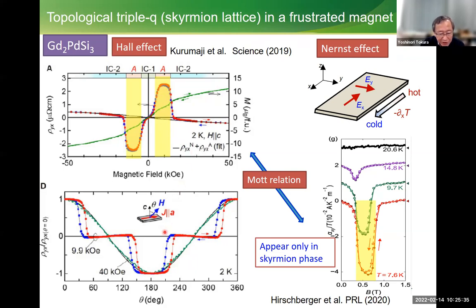And importantly, if you apply the magnetic field along this c axis, and then the magnetic field is gradually tilted, then at some regions the Hall effect is almost quantized. But suddenly it goes to zero, which means the skyrmion lattice just disappears. But in the opposite direction, again the skyrmion lattice shows up and also shows the flat-topped structures.